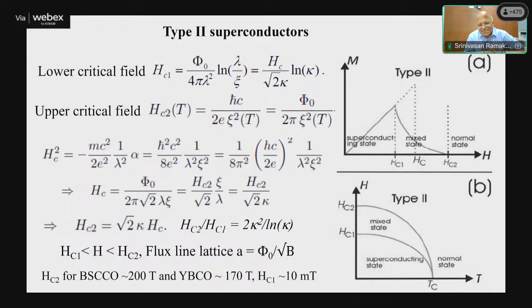And you can see that this forms a vortex lattice, and that can explain the magnetic properties even of high Tc superconductors. Hc2 for BSCCO is about 200 Tesla, and for YBCO about 170 Tesla, whereas the lower critical fields are extremely small. So they are called extreme type 2 superconductors because the kappa value, the ratio of Hc2 to Hc1, is extremely large.